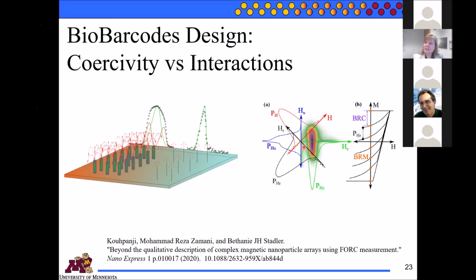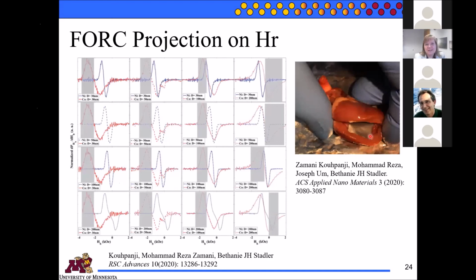So Reza has actually studied various ways to project this FORC curve onto the HR axis. So this is the measured reversal field. Every time you go to the reversal field, you plot the FORC parameters that you see plotted a lot in FORC measurements against that HR. We call it the projection method because we're projecting the FORC onto the HR axis. And the other thing he'll do is look at the remanence. After each reversal field is applied, what's the remanence? And long story short, it turns out that remanence is a pretty good thing to look at. And so this is one example of that.